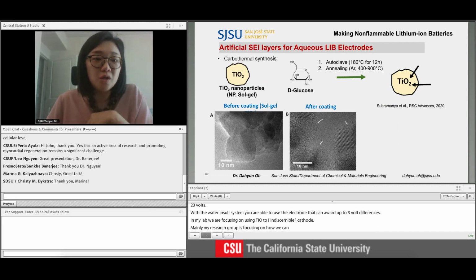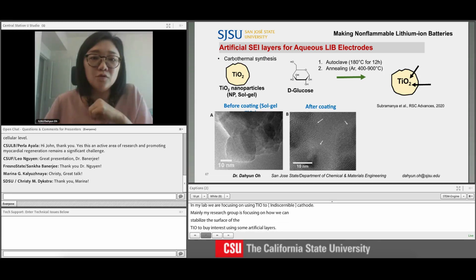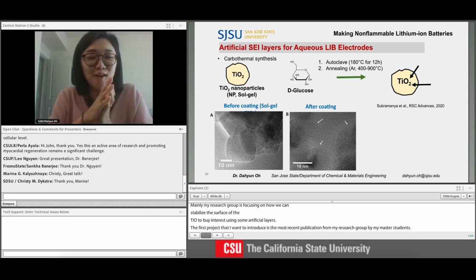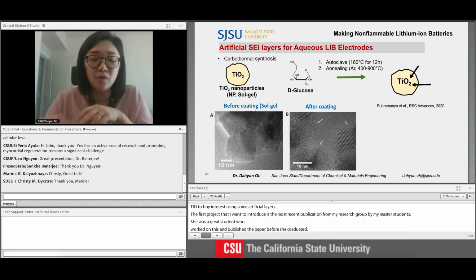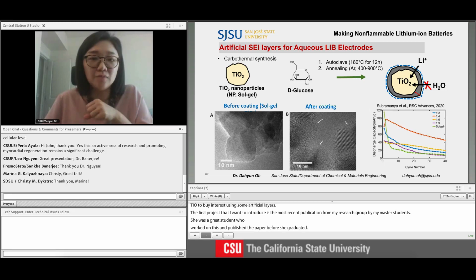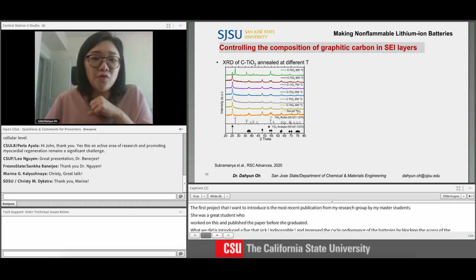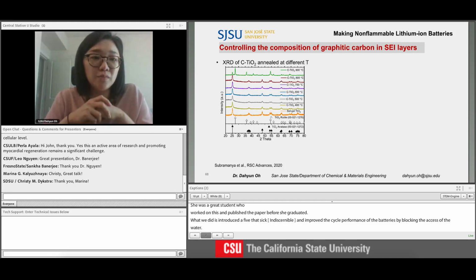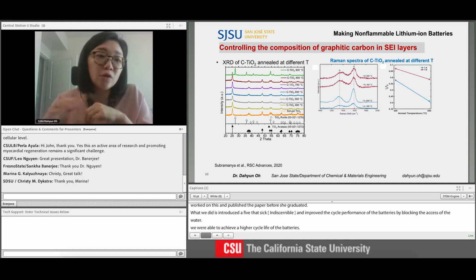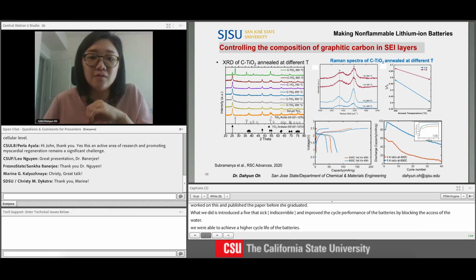The first project that I want to introduce is the most recent publication from my research group, by my master's student, Usha. She was a great student to work on this and wrap up the project and publish the paper before she graduated. What we did is introduce about a 5 nanometer thick carbon layer around the TiO2 nanoparticle and improve the cycle performance of the batteries by blocking the access of the water. Here you can see that at a certain composition we were able to achieve a higher cycle life. She also found certain temperature ranges to make the carbon layer, which are relatively low temperatures, to pyrolyze the glucose. The best performance was achieved at around 600 degrees Celsius.